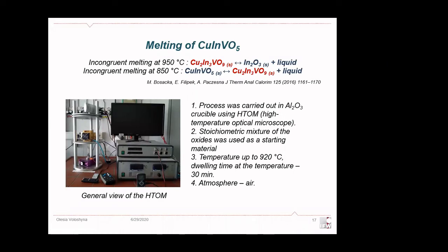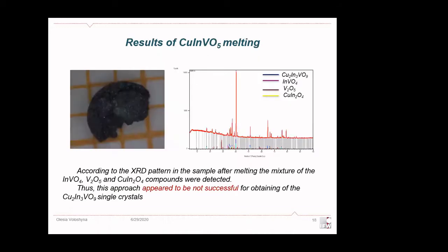the slide, the only thing being that as a raw material we used only a stoichiometric mixture of the starting oxides, and as a result we obtain such a batch. The XRD result for such a batch proves that in the end we obtain just a mix of different compounds. So such an approach appeared to be not so successful for obtaining our goal compound.